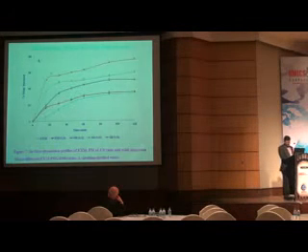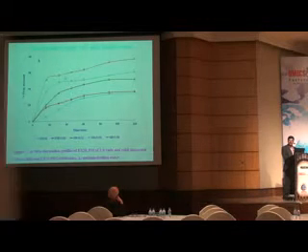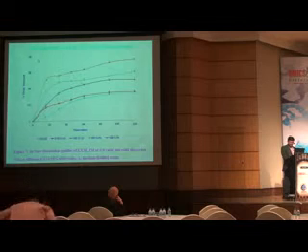So the degree of crystallinity was understood with the X-ray diffractometer. A was pure ebastine, which shows some crystalline nature, and B was PEG 6000 with 2 probable peaks, and the physical mixture with 2 peaks of PEG along with some peaks, whereas in the solid dispersion, that is D, we could not observe that, and the degree of crystallinity was observed to be decreased when compared with the pure drug.